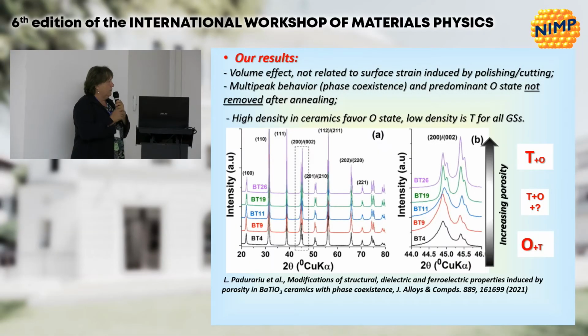Our results are showing a volume effect because we didn't use any cutting machine. These are just as-prepared samples. They have a multi-peak behavior at room temperature. And because we also wanted to rule out the role of porosity, we prepared samples having the same grain size but different porosity levels by using polymer sacrificial templates. We have a level of porosity from 4% to 26% here, showing clearly the inverted peaks, which are nevertheless multi-phase, with the tendency to be orthorhombic when they are dense and more tetragonal when they are porous.